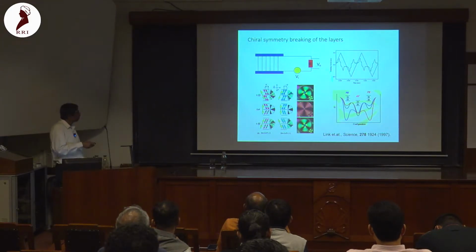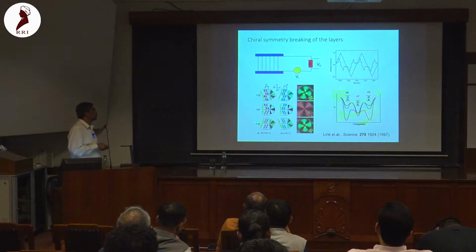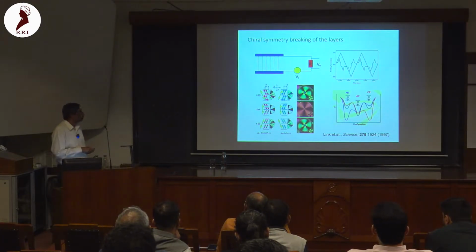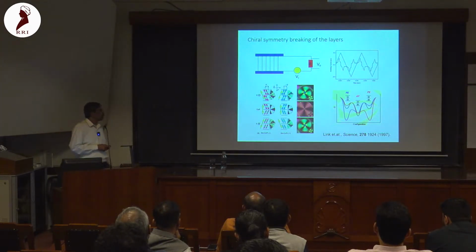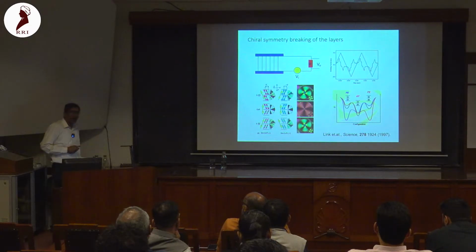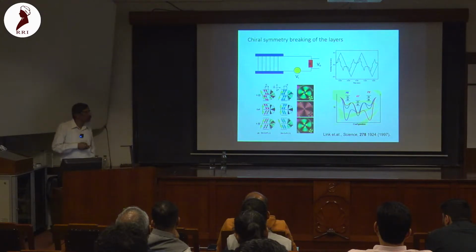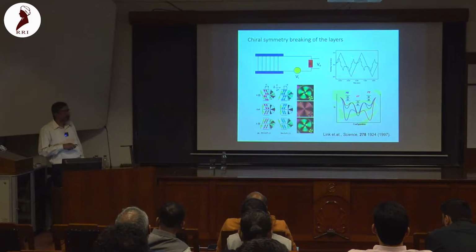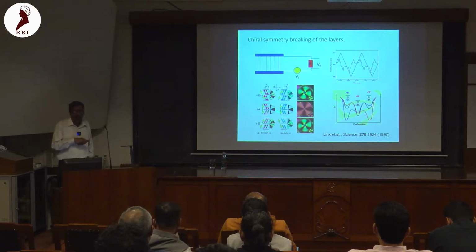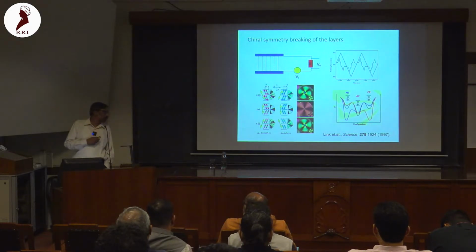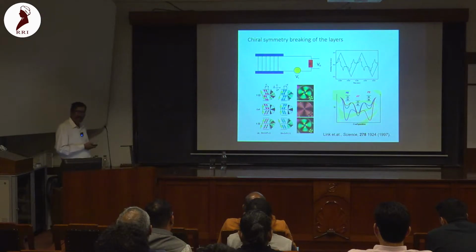you can figure out the polarization state of these materials, and of course you can do XRD and other studies and see whether there is a layer structure and so on. Actually, the molecules of these materials are of the order of, let's say, 2 to 5 nanometers, and we do not have direct technology to see those molecules. So all these studies you have to do on a macroscopic scale, and you have to infer the structure of the molecules from those measurements. That is the difficulty of understanding the properties of these materials, or the actual detailed arrangement of the molecules.